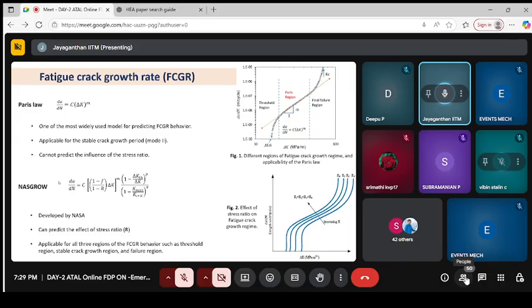Delta K accounts for the stress intensity factor, and that is being plotted. We have several zones: the threshold zone, the middle region called the Paris zone, and the third one, final failure. The crack growth also goes through several stages: non-linear at the beginning, linear in the middle, and non-linear at the end. The middle portion is captured accurately by using Paris law.